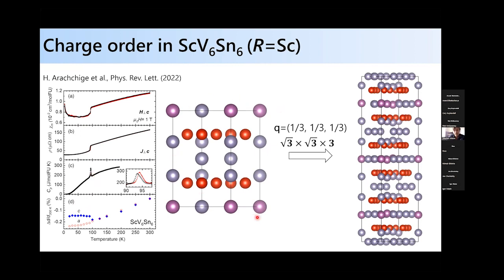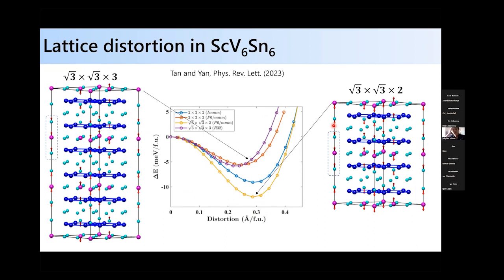And indeed, when you look at the structure of this system as you cool below this transition, there's a √3 by √3 by 3 enlargement of the unit cell with a wave vector of (1/3, 1/3, 1/3). From first principles, calculations by Binghai Yan's group show that if the structure is unstable to distortion, the most energetically favored distortion is actually a √3 by √3 by 2. So the unit cell enlarges in plane by √3 by √3, which is consistent with the experiment, but only doubles along the c-axis, whereas this is the experimentally observed distortion.